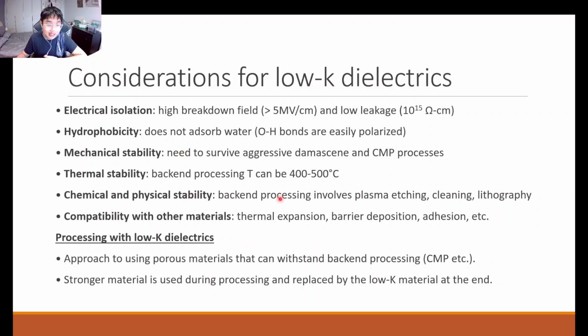And it also must be compatible with the material that is being layered on and the material that is being laid upon it. So it needs to have similar thermal expansion coefficients with the other materials connected to it. It needs to have good barrier properties. That means there's not too much interdiffusion between the layers through your low-K dielectrics. As well as adhesion. The layers that you deposit on it must be able to adhere well to it, so that there's no delamination or separation that can occur.